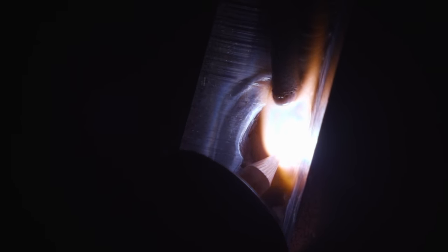Since I got it set on there now, I'm rearranging myself to get a little bit more comfortable. I turned the machine up to 120 amps to give more power. You see my puddle get bigger, then I'm just going to walk her up. I'm pausing, doing like slight hesitations, let that puddle wash into that bevel and melt that bevel really good, right on my toes.